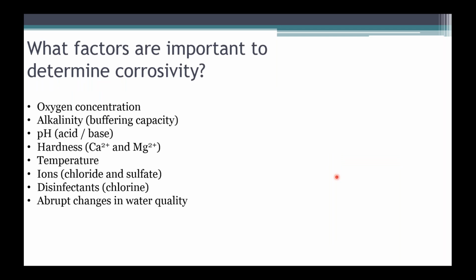Okay, so what are some of the things that make water corrosive? A lot of these factors are probably not that unexpected, but in many cases there's a sweet spot that really minimizes corrosion. One example would be oxygen concentration. Very high oxygen concentrations can accelerate the corrosion of metals and cause them to become mobilized into the drinking water. But at the same time, very low oxygen can promote the growth of microorganisms that cause corrosion through other processes. So the goal is usually to keep oxygen concentrations in an acceptable range.